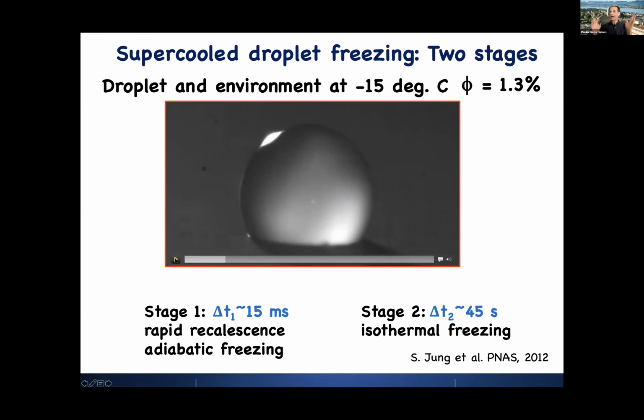Boom, suddenly something happens. Those ice crystals that I mentioned, the embryos that I mentioned earlier, become stable and they grow explosively, all right? By growing, they release heat, and then when they release heat, they heat up the droplet. And the droplet from minus 15, you will be amazed if you're not familiar with this, within milliseconds, because now you have a mixture of these ice crystals and liquid, goes to its equilibrium temperature 0. So within milliseconds, the temperature, which is in a cold environment of minus 15 degrees, reaches 0.